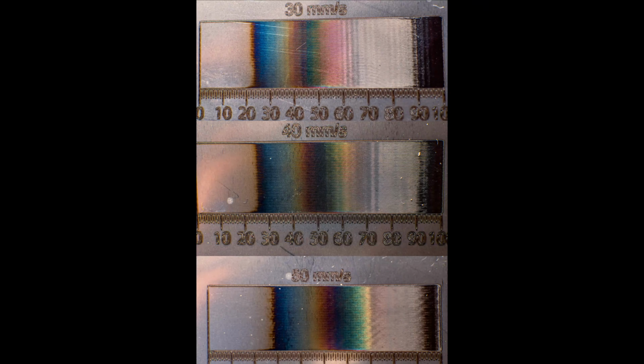It was also interesting to see that the same colours appear at different percentages of power depending on the speed of the laser. This makes sense because as the laser starts moving faster, you need to use more power from the laser to heat up the surface of the steel to the same temperature and achieve the same colour. To reduce the amount of time it takes to run each file, you can then speed up the laser but run it at a higher power and get the same colour output.